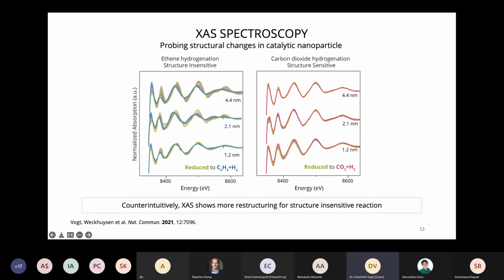And again, comparing ethene hydrogenation to carbon dioxide hydrogenation, structure sensitive reaction, structure insensitive reaction, and there we saw something counterintuitive. Now we see that actually the structure of the catalyst is changing much more significantly for the structure insensitive reaction than it is for the structure sensitive reaction. We see that the wiggles going from green to blue, going from reduced to reaction, are very significantly changing. This indicates quite a big local restructuring. And again, for the structure sensitive reaction, we only saw a little bit of oxidation basically in the beginning of the spectrum in the XANES.